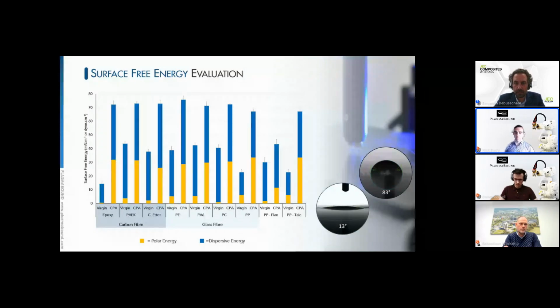Looking at future-focused adhesives, or sorry, substrates, such as polypropylene with flax or polypropylene with talc, which is used in the automotive industry quite a bit, these two materials do demonstrate an increase. They're not as high as the previous materials in the context of before and after. However, it's important to point out in the case of the flax, it's very difficult to do this treatment without causing damage to the flax structure. So the reason why the energization of it from a polar perspective is lower is to prevent the damage of the organic material within the flax structure.